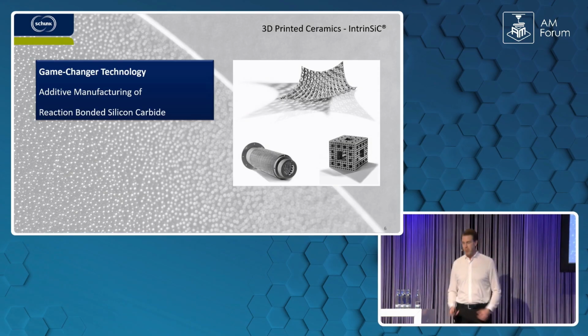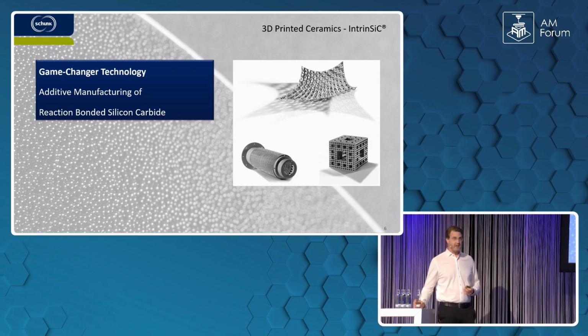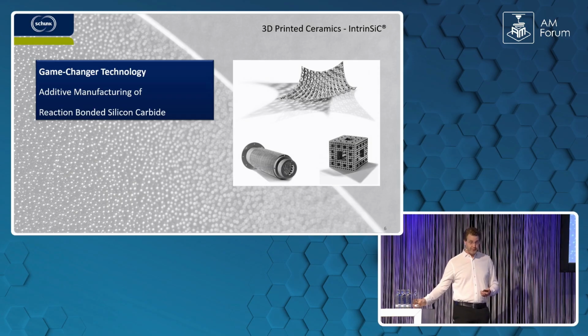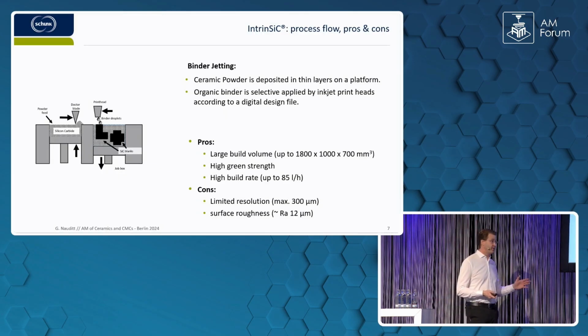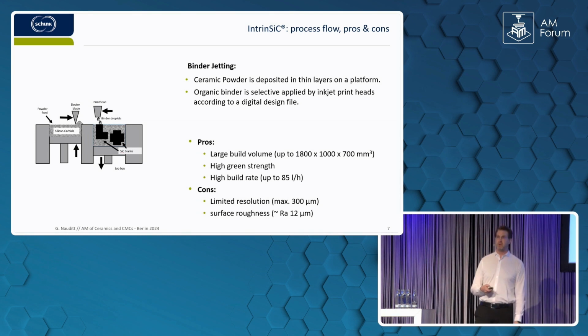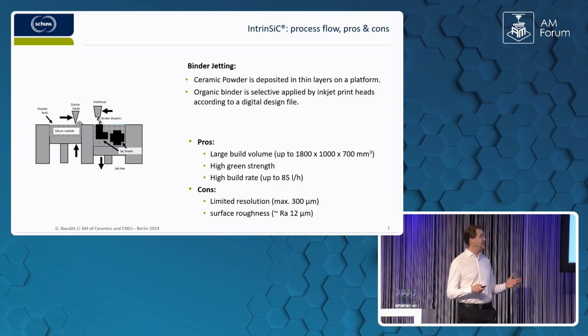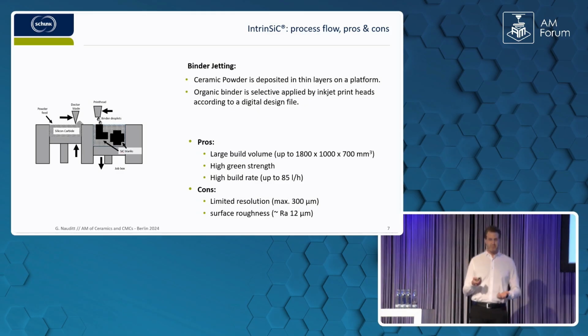And meanwhile, we invented a really good technology, which for us was really a game-changing technology. We are printing reaction-bonded silicon carbide. And to do this, we use a powder bed printing process with binder jetting. I think you all know this process. We are using silicon carbide powder for this, silicon carbide powder grains. And an organic binder is then printed inside of these grains to build the part.